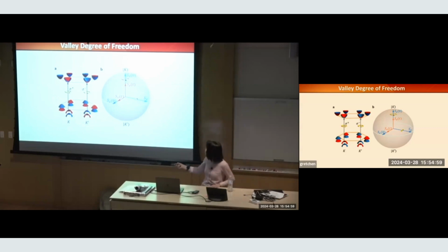What that really means is the spin states occupying the top of the valence band and the bottom of the conduction band in the two valleys are flipped. As a result, the light emitted from a transition in one valley versus the other valley are reversed in the photon chirality. So if you want to excite a transition in the K valley, you just use sigma plus light. If you want to excite a transition in the K prime valley, you reverse the helicity of the light. So there's a nice relation between chirality of the photon emission and where they are in the valley.